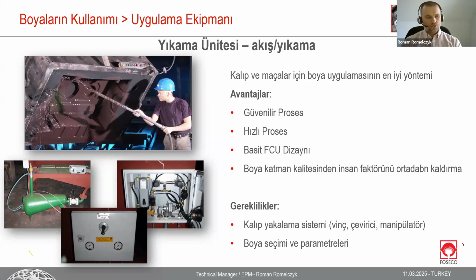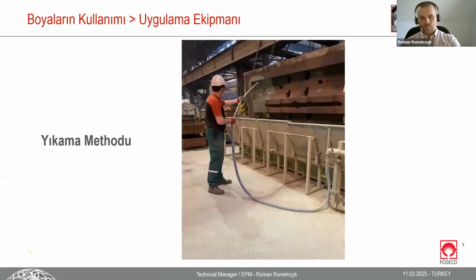But in general, this is a super fast and very, very good application method, we can say dedicated for complicated shapes, when we expect very high refractory resistance, so the coating has a chance to impregnate the mold. We can apply 2 layers, as I presented before: first layer by flow, second by spray. So this application method gives us a big chance to have nice casting quality.